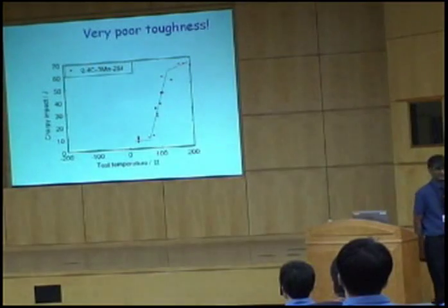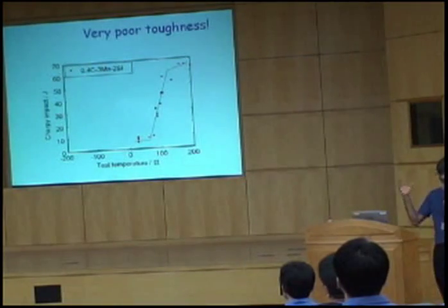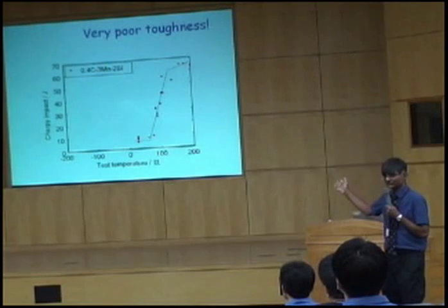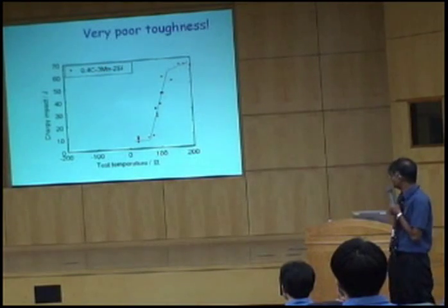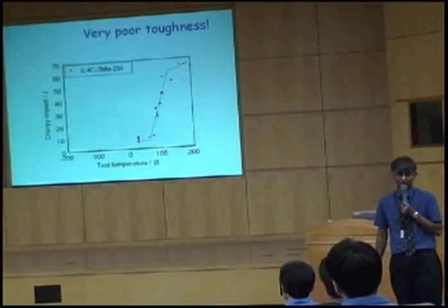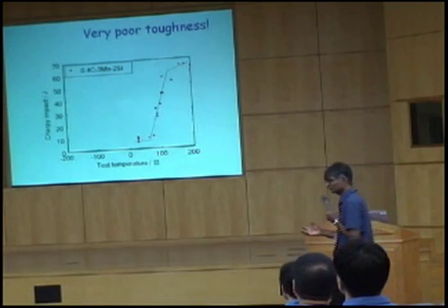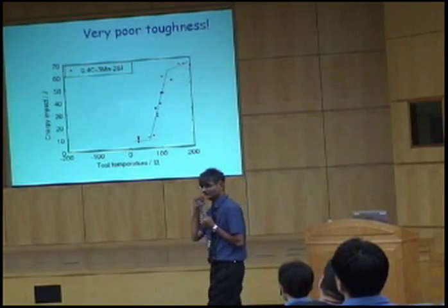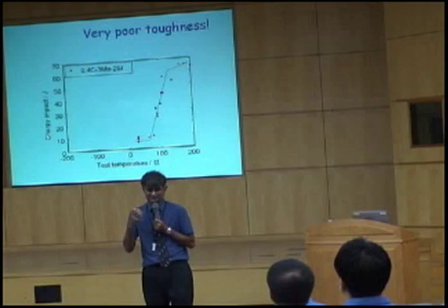Well, when you measure the toughness, it's very bad. Okay? There's something really wrong. You know, you can look at the impact transition temperature, it is of the order of 100 degrees centigrade. So we have this beautiful microstructure which should have good toughness, but it's very bad. Why is that?